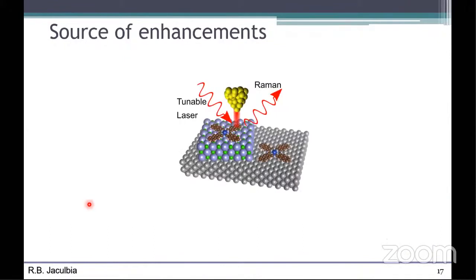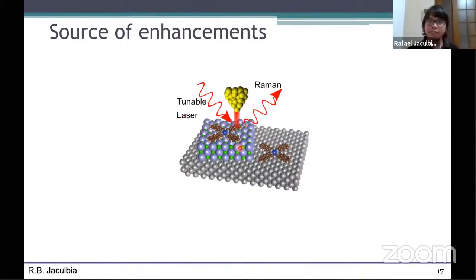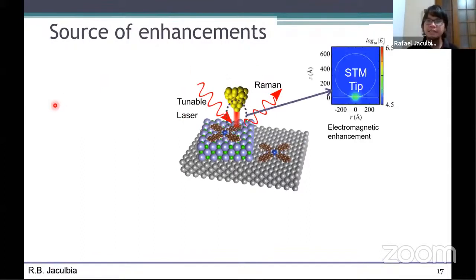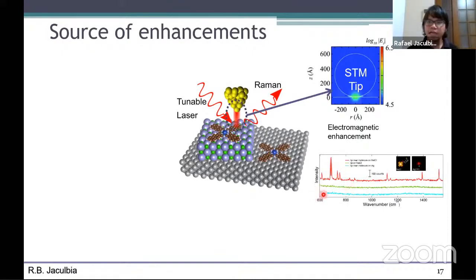Then what does this imply? As I said before, there are several sources of enhancement in TERS. First is the electromagnetic enhancement. However, as I said, the molecule on the metal shows no Raman signal. But in this experiment, we just moved the tip from the molecule on the sodium chloride to the molecule on the metal, and there is signal here and no signal there. This observation cannot be explained just by the electromagnetic effect, because the same tip and the same laser energy are used. So electromagnetic enhancement cannot answer why there is signal here and no signal there.